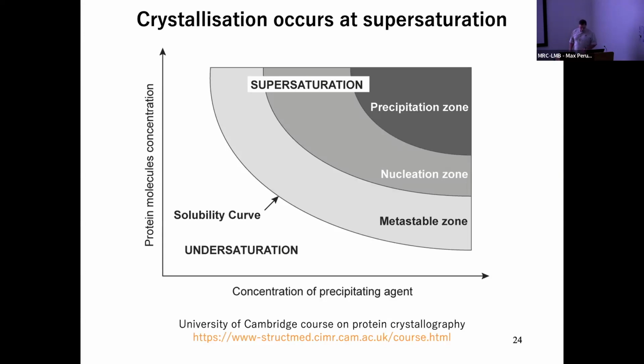In practice, many other parameters should be considered. For example, transition from aggregation to crystal growth is regularly observed for large and complex samples. Also, the oligomeric state of a sample may change with the saturation level and the pH. It's very rare to have such phase diagrams, but I remember seeing one that actually showed the different oligomeric states of the protein. Protein stability varies also with other parameters like surface tension, etc. Growth preferentially occurs in the metastable zone, at a lower saturation level than nucleation.